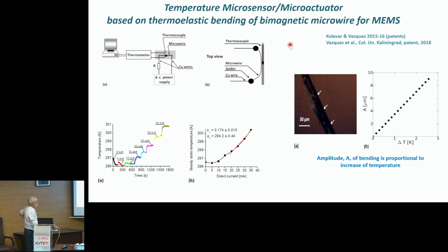The temperature behavior of the internal magnetic layer, the external magnetic layer, and the pyrex is different because of the different thermal expansion coefficients. So when you increase the temperature a little bit, the microwire bends a little bit. This bending is actually very significant around room temperature for particular microwire compositions. This is the amplitude of the bending, proportional to the radius of curvature, as a function of temperature increase around 25-30 degrees centigrade. So it's very sensitive to measure the temperature, and the response time is also very fast.